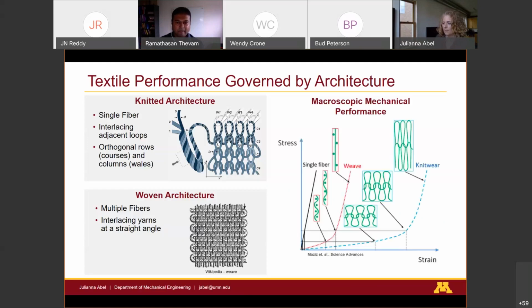I really like how it was shown in this article from the Jaeger group, comparing the performance of a single fiber. Regardless of what base material you're using, you have some initial fiber performance, and as you stretch this material, you'll see whatever performance is given. Once you integrate it into woven structures, you have these slight bends that you're inducing, and as you pull on it, it's a little stretchier than the base material itself. And as you integrate it into a knitted structure, you have large bending deformation, so you get a much more flexible structure, and you get this J-shaped curve. This J-shaped curve is interesting for a lot of reasons. We like it because it's really close to human tissue, so you're getting a mechanical response that's closer to what your human body exhibits. So it's easier to create applications that will match with your body's performance.